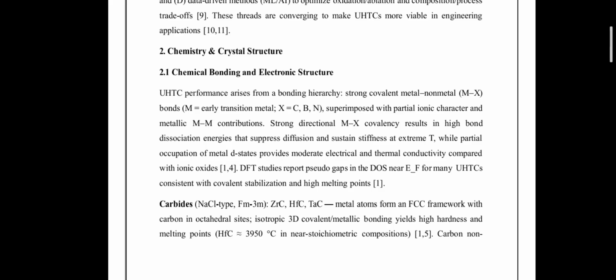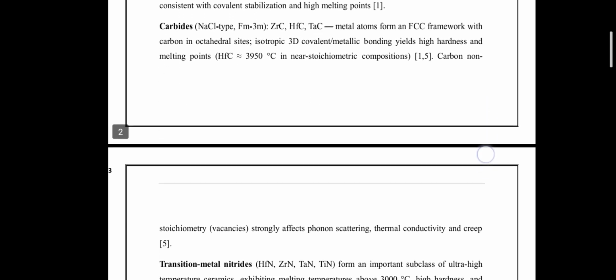So, when we talk about the electronic structure, density functional theory calculations reveal a pseudo gap in the electronic density of states near the Fermi level for many ultra high temperature ceramics. These pseudo gaps indicate covalent stabilization and correlate strongly with the high melting temperature and thermodynamic stability. This electronic structure explains why ultra high temperature ceramics retain stiffness and phase stability even near 3000 degrees Celsius. Now we will discuss the carbides.